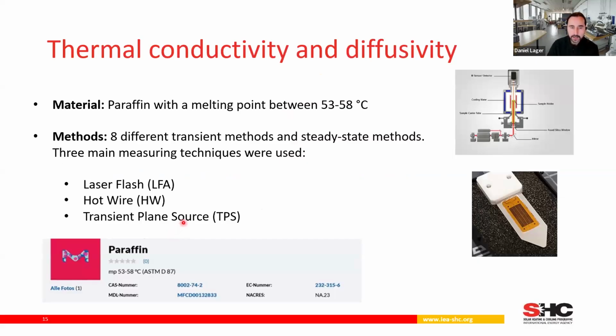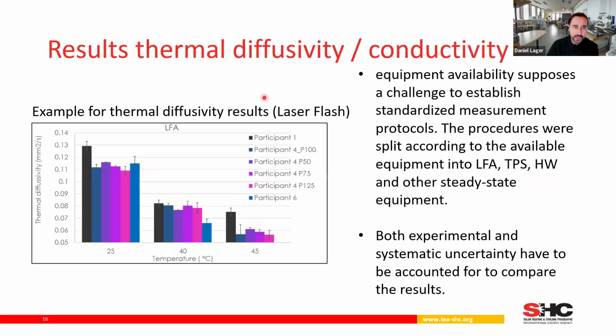Here we had 8 different methods we compared to each other. And we measured a paraffin wax with a melting point between 53 and 58 degrees centigrade. You see the material here. And the main 3 methods we were looking at were laser flash, hot wire, and transient plane source techniques. And I show you here one result of the laser flash round robin.